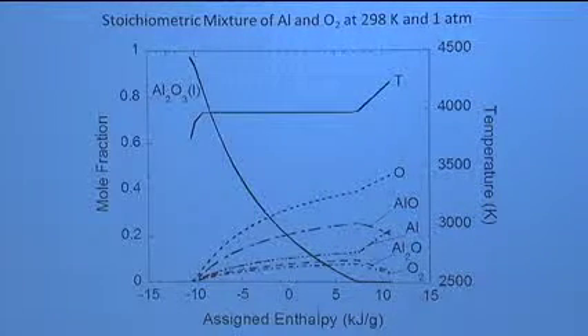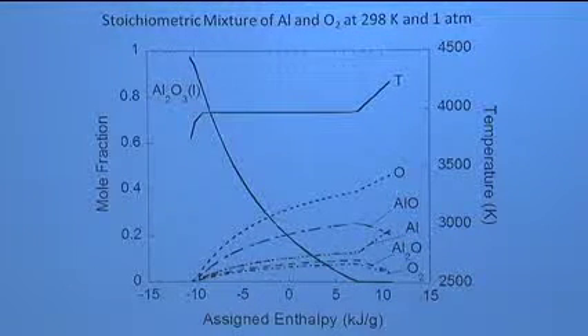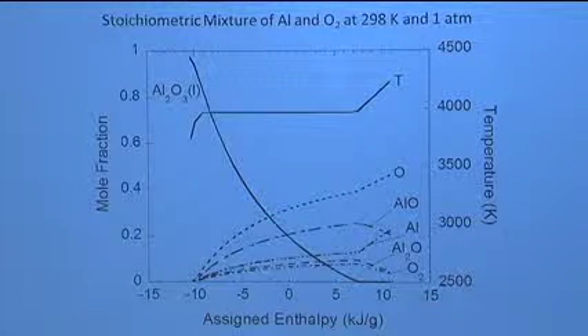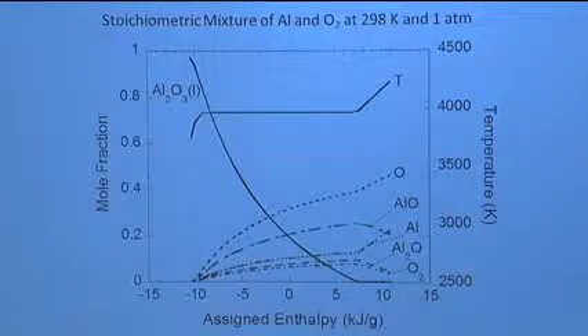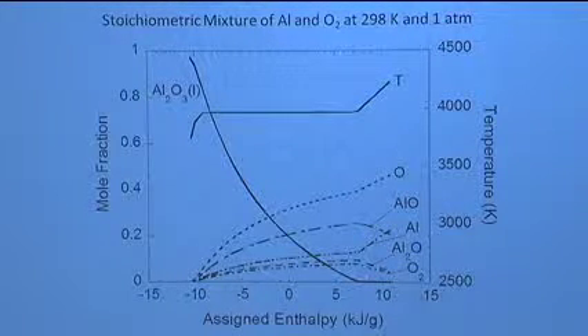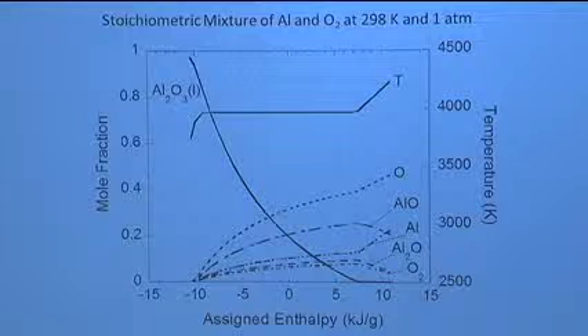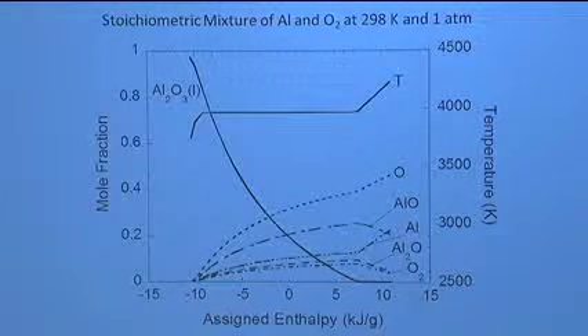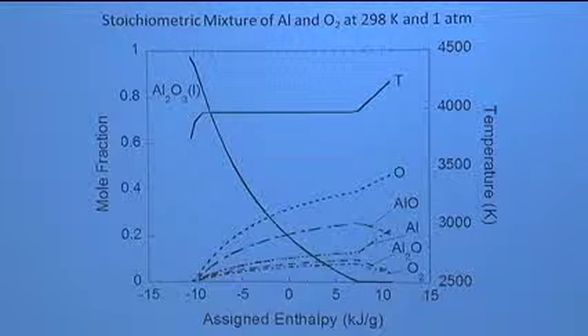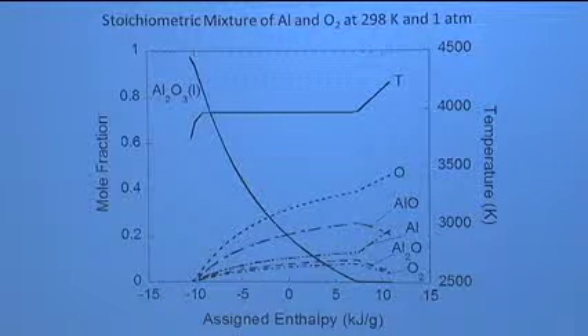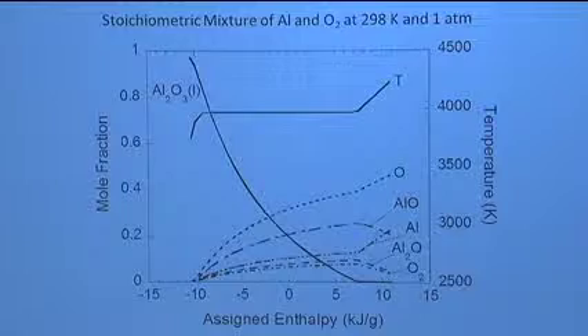condensed phase oxide. If I add energy to the system, you can see the temperature still stays the same, but the amount of alumina changes, and I start getting more and more gas phase species until I get to an energy level out here. And at that point, all the condensed phase material disappears and the temperature starts to rise. So what you're seeing here is essentially the reaction temperature sort of being controlled by a pseudo-phase change of the final product, okay? And this is sort of the concept of this limiting flame temperature.